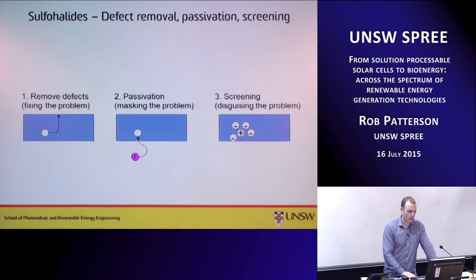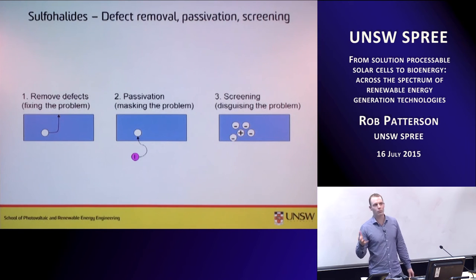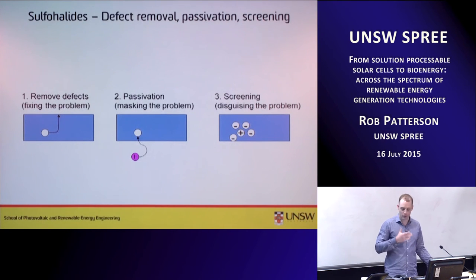So when we make solar cells, the first thing we would like to do with our material is get rid of any problems. This certainly is a lot easier if we can anneal a low melting point material at 100 degrees C rather than 1,000 degrees C. In many cases, these solution processable materials have lower melting points. We're in fact limited to lower melting points because in the chem lab, we can only go up to 200 or 300 degrees in our solvents.